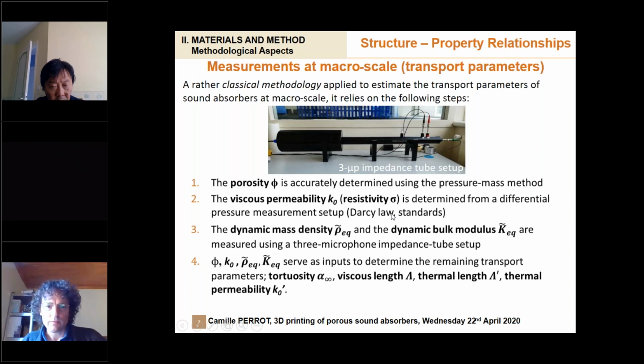And I would recommend measuring frequency-dependent response functions, let's say the dynamic mass density associated with visco-inertial effects, and dynamic bulk modulus associated with frequency-dependent thermal effects, that you can get from a 3 microphone impedance tube setup, or eventually a 4 microphone impedance tube setup. And based on this set of parameters, you have basically 4 input parameters, and you can get the remaining ones, which are the tortuosity, the viscous length, the thermal length, and the thermal permeability.